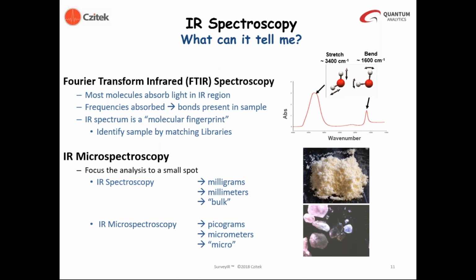So if we look at infrared spectroscopy and compare it to infrared microspectroscopy, infrared spectroscopy allows us to analyze materials in the milligram mass range and in the millimeters size regime. And it's a bulk technique, if not coupled with a microscope that allows one to pass infrared radiation through it. So when we do that, we can extend the detection capability down to picograms, 10 to the minus 12 grams, and in the micrometer domain. So with a beam condensing microscope optics, we can analyze microsamples using infrared spectroscopy.